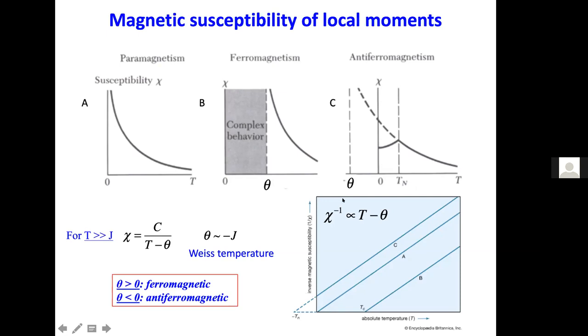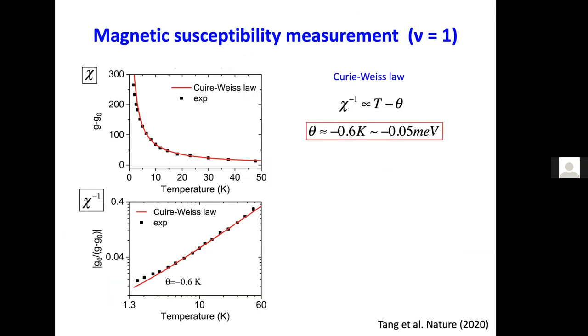So you can plot 1 over chi. I told you that by looking at the difference between left and right circular polarized absorption, you get the net magnetization, and from there you can get the susceptibility when you apply a small magnetic field. This is the result - the susceptibility...